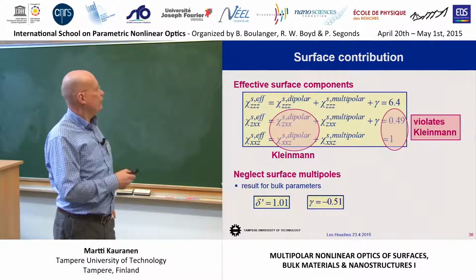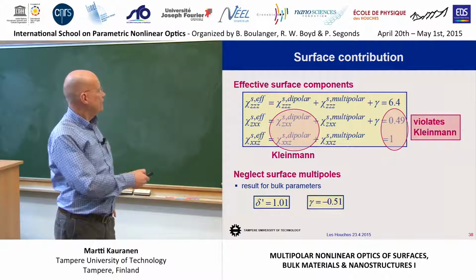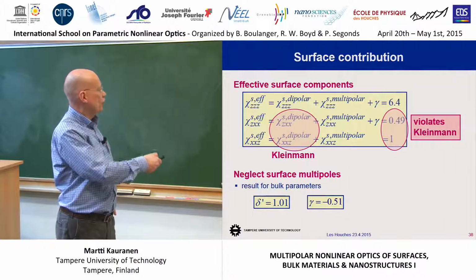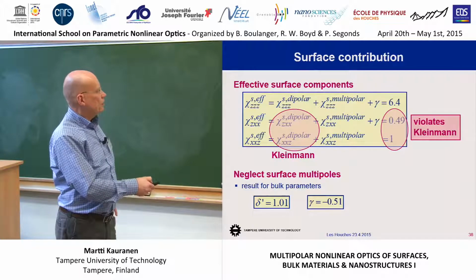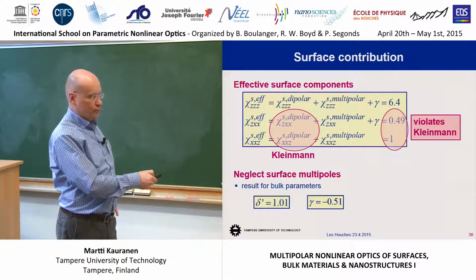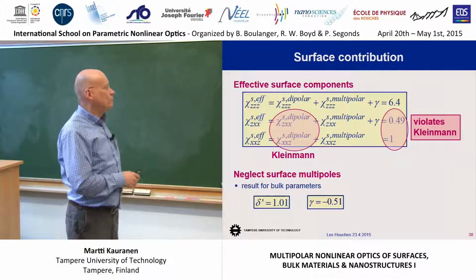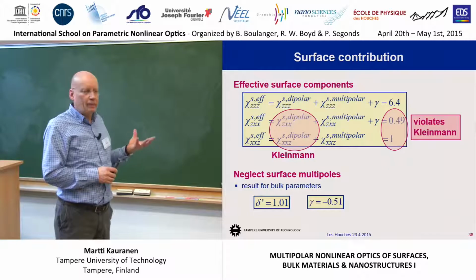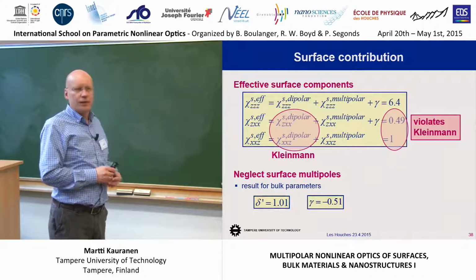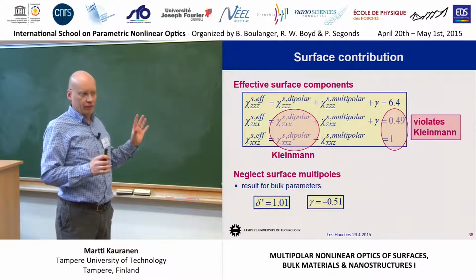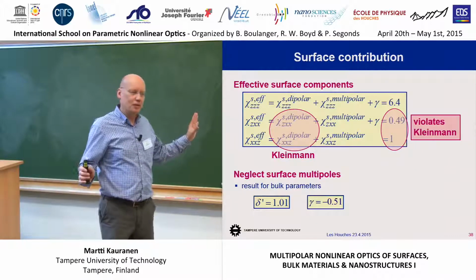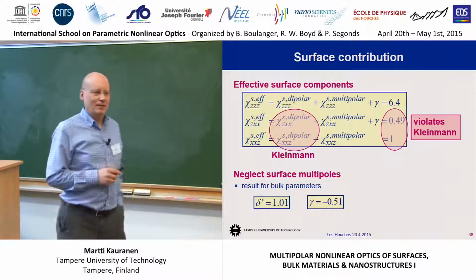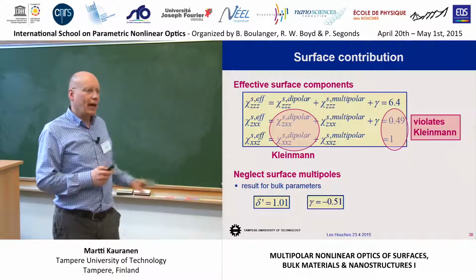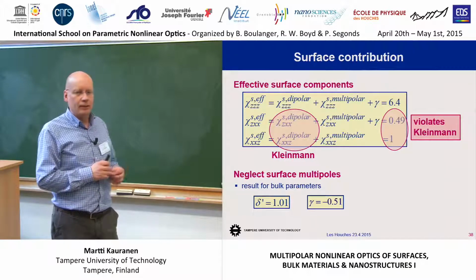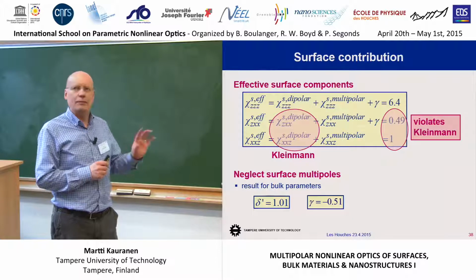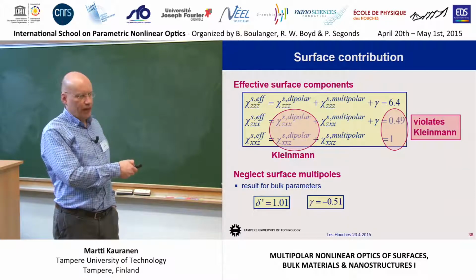Therefore, if we only had a surface response, then these two components would have to be equal. Here, they differ by a factor of 2. And my claim is that a factor of 2 is a big difference. So clearly, Kleinman symmetry is not fulfilled here. Actually, I'm not a big believer in Kleinman symmetry in any case. People take it to extremes in some cases. There are actually papers where people have addressed how valid Kleinman symmetry is in some context, and you can always measure some deviations. But this is really far away, okay?